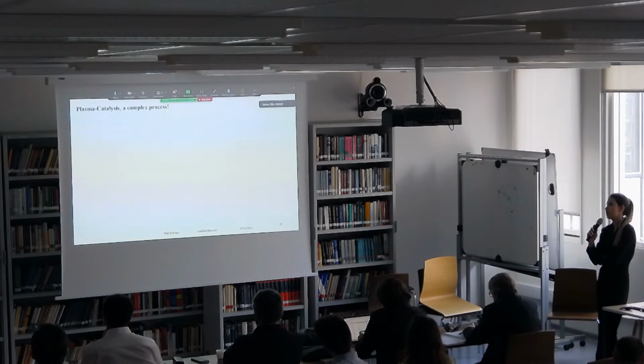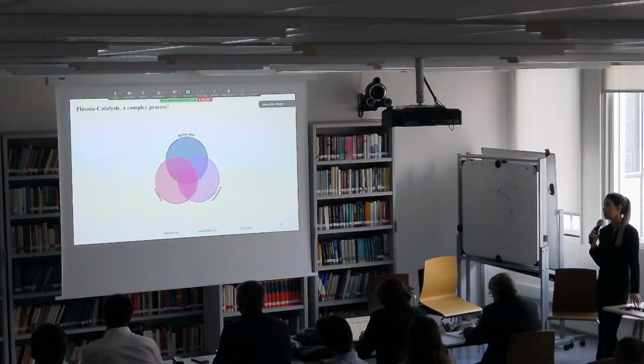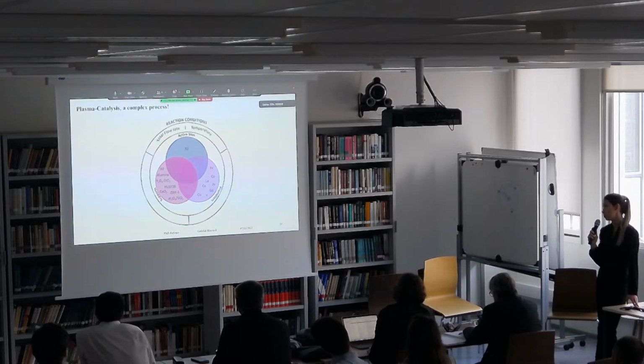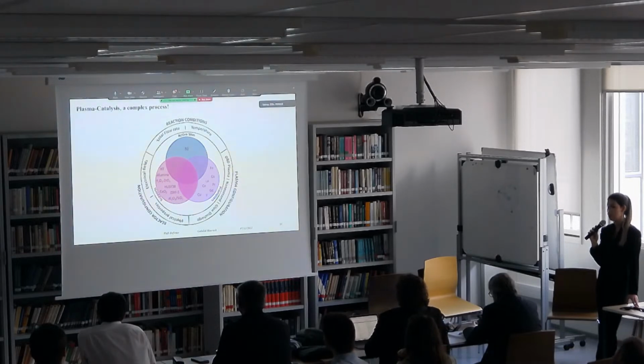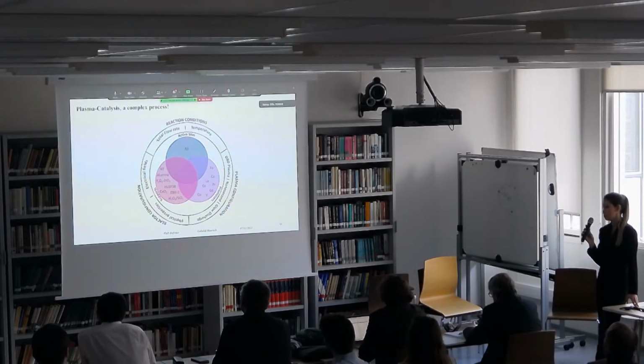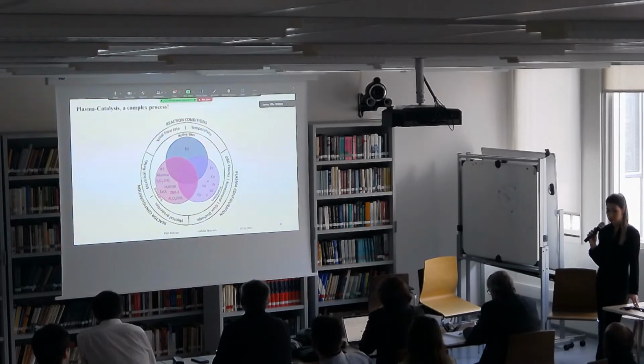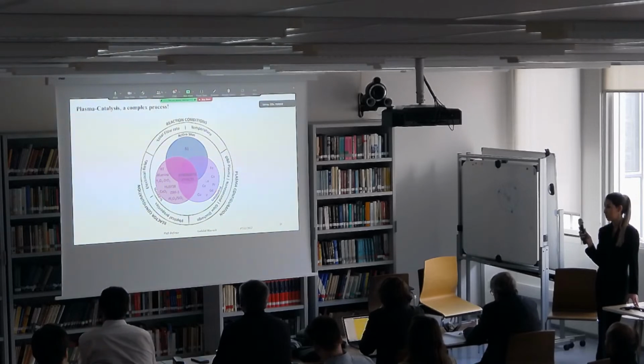However, it should be said that plasma catalysis is a complex process. In the heart of this process, there is a catalyst containing an active phase, promoters and support, each of which can be from different materials based on their application. As the body of the system, there is plasma, which also has different parts. By varying the reaction conditions, the catalytic performance can be changed, while by varying the reactor configuration, the system can be optimized. And finally, using different plasma configurations can change the catalytic performance. All of this together, plasma and catalysis can affect each other, which is called synergistic effects, meaning that the combination of these two, plasma and catalyst, can have a more beneficial effect compared to using each one of them alone.